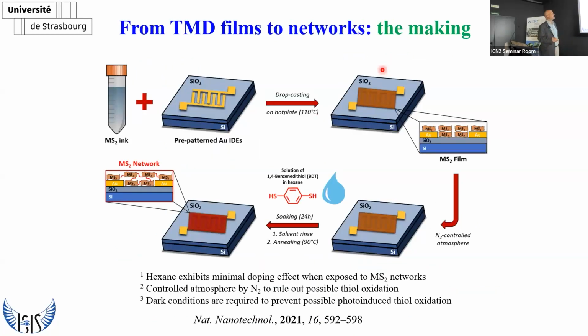Now, how we fabricate the device is pretty simple. We took a commercial substrate of silicon dioxide from Fraunhofer, which exposed some pre-patterned gold electrodes. The ink coming from Johnny Coleman, we drop cast in between the two electrodes, and then we obtained what I call films. So here is where me and Johnny still disagree. I call films where the flakes are disconnected. And then actually we put this in a controlled atmosphere.